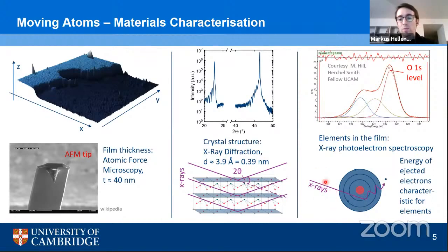But this time, we want to use the energy of the X-rays to kick out electrons from the materials, because the binding energy of electrons to their atoms is characteristic of different elements. So if we measure the energy that we need to kick out electrons out of a material, we can then see what materials we have in our film. And with these two together, we know the crystal structure and we know the elements in the crystal structure. We can then be quite certain that we actually get the materials that we want.